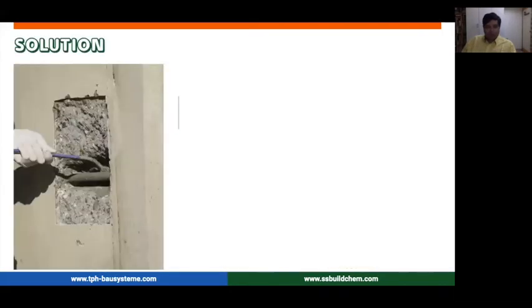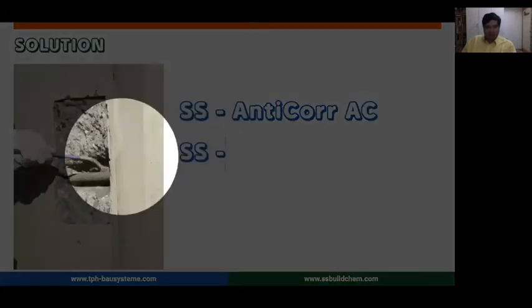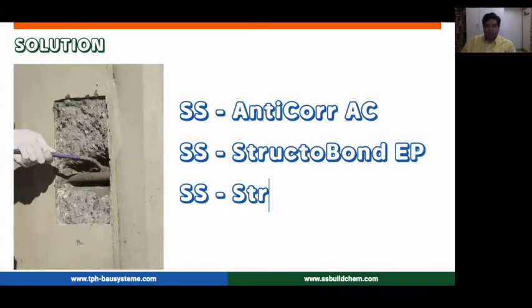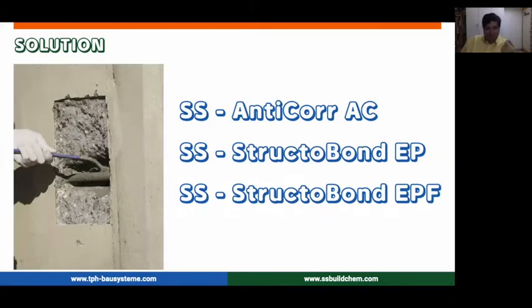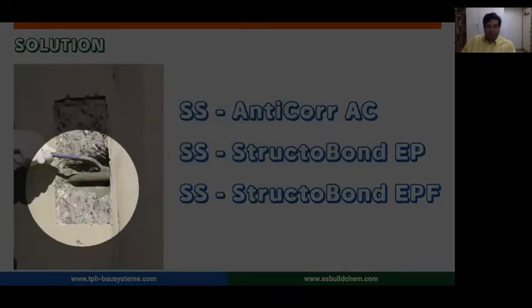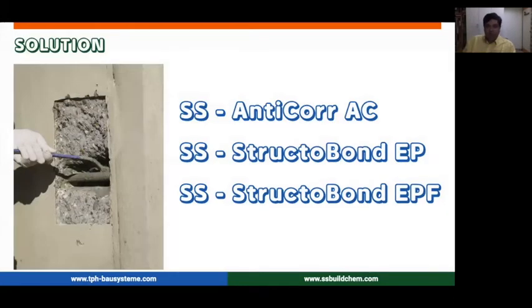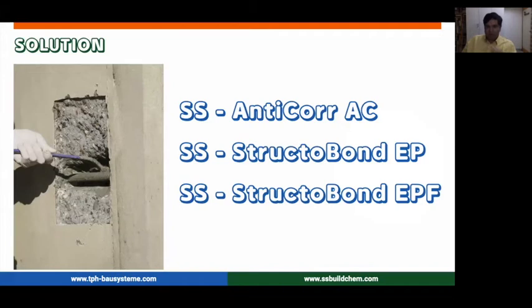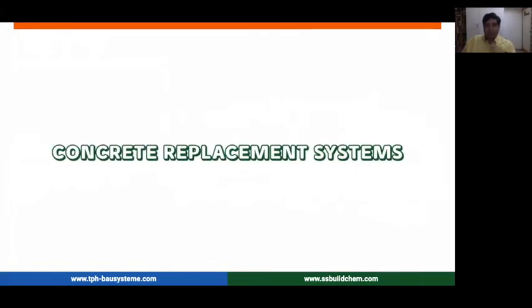Once you do your substrate preparation and your corrosion protection, then you look at the bond coat. A bond coat is simply making a bridge between your existing substrate and the mortar to be applied. In our case, the same material, the SS anti-corrosion, that functions as a corrosion protection also functions as a bond coat. So you can just mix up the same material, apply it onto your concrete substrate, and then apply the mortar fresh on fresh with that. In case epoxy is needed for things like floors or somewhere a higher bond might be needed, we also have other epoxy-based systems available for that. But again, for concrete repair, it's better to use cement-based materials. With cement to cement, the performance and the compatibility is much better.